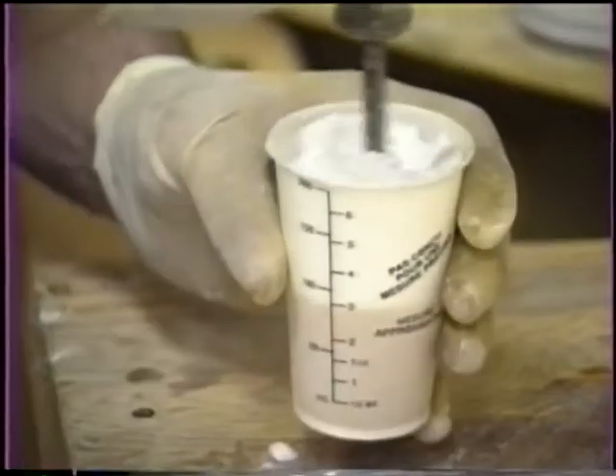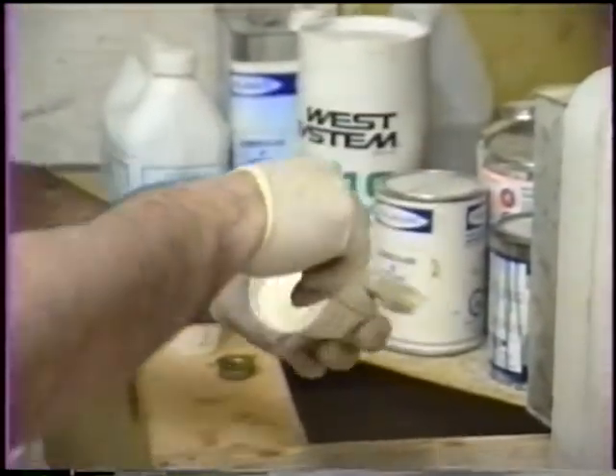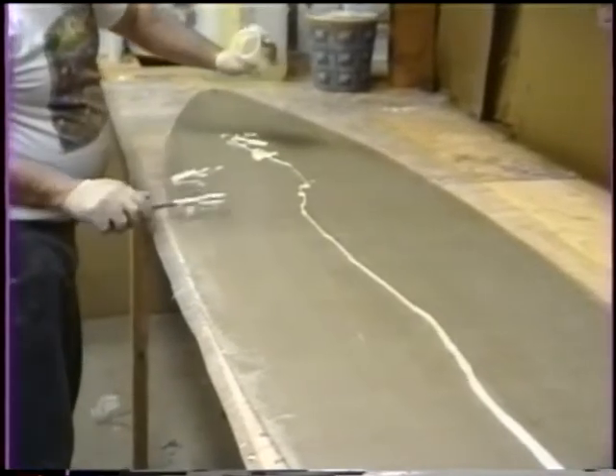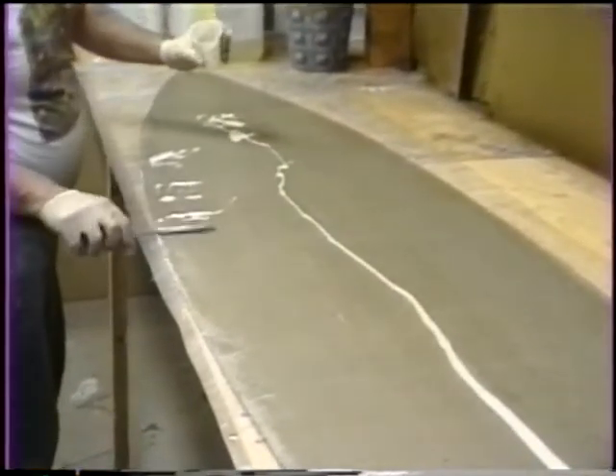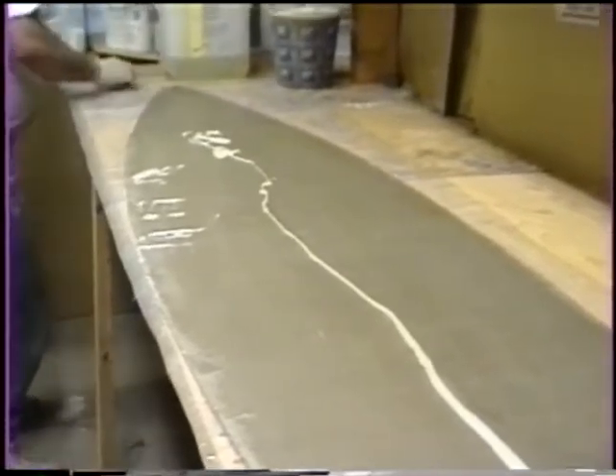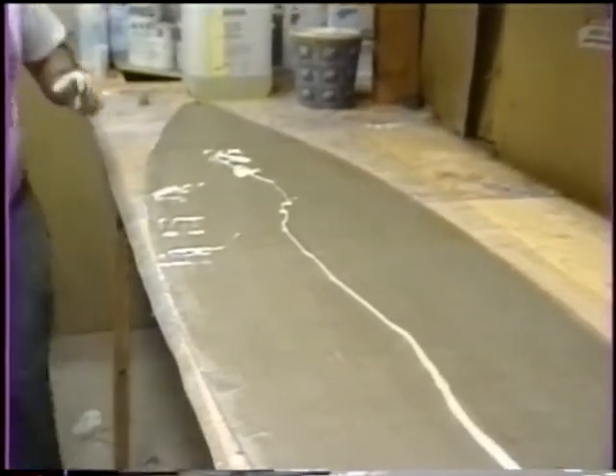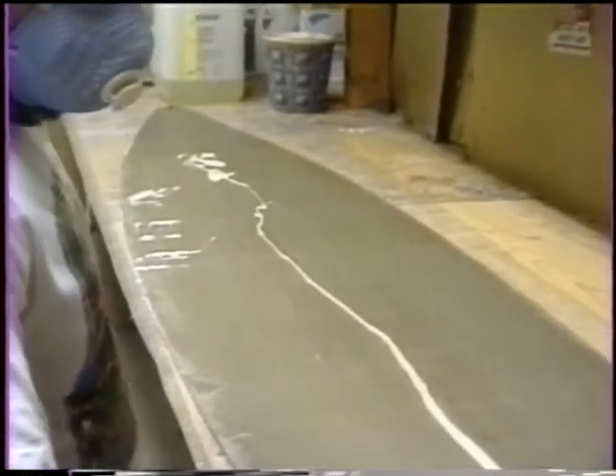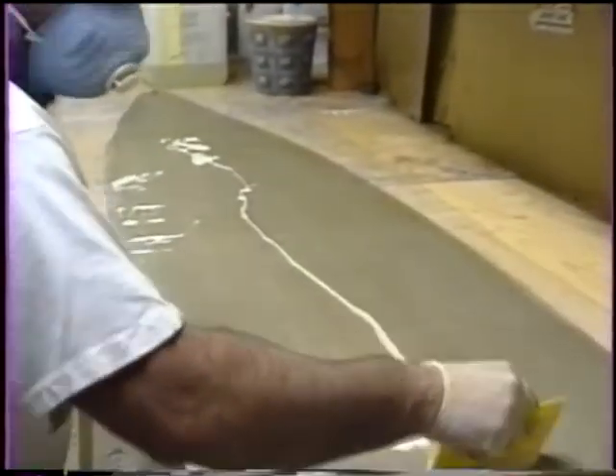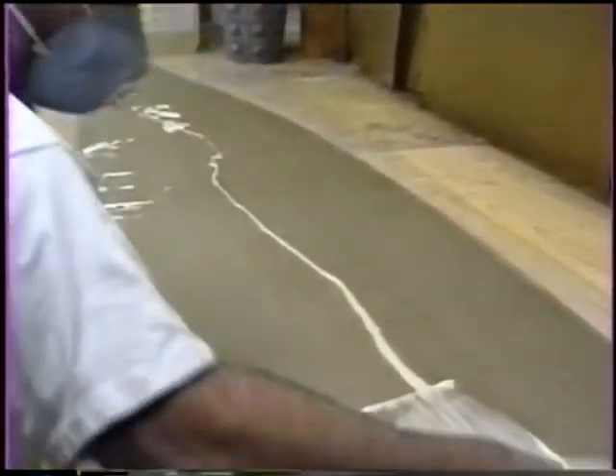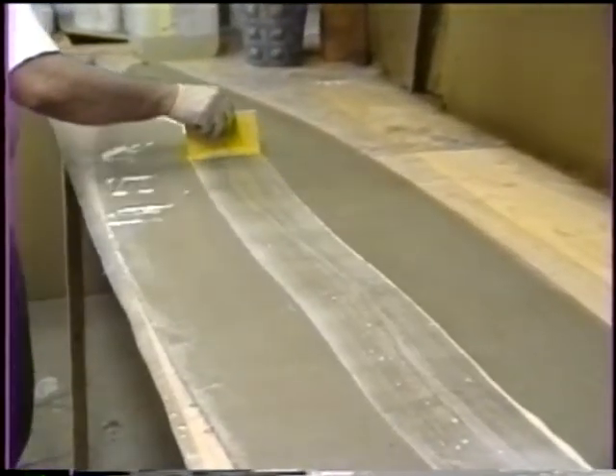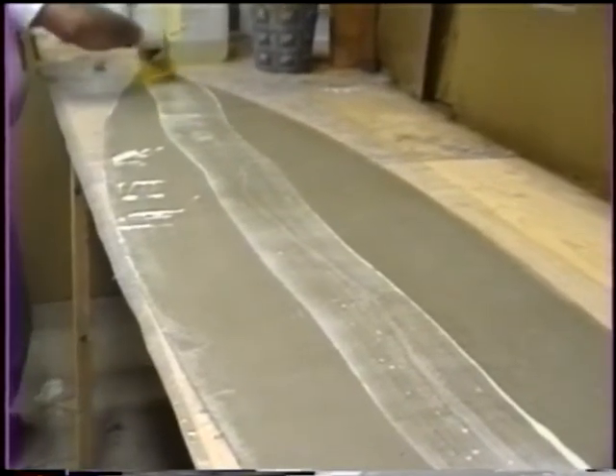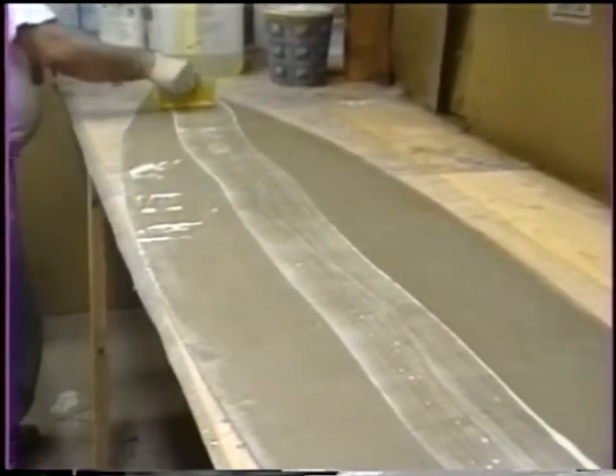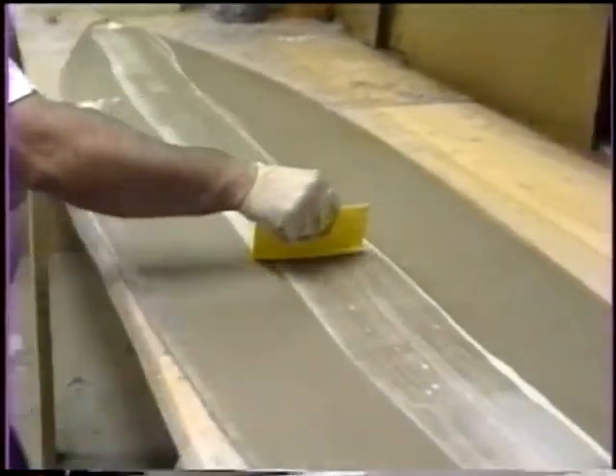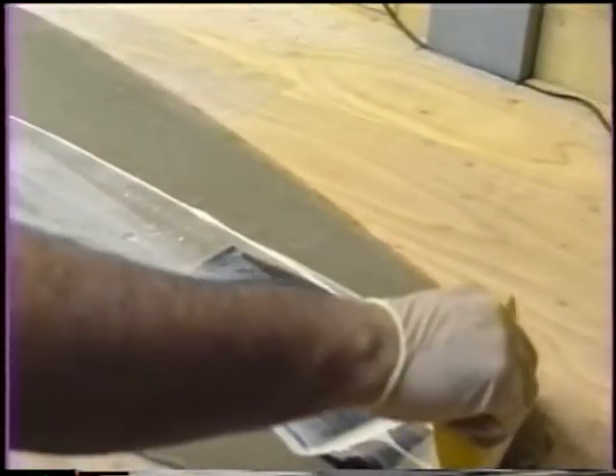Some weight-saving and bonding tips are to mix up microspheres with some of the resin and fill the coarse surface of the high-density foam before covering with cloth. Another tip for a long-lasting board is to install a long 1.5 inch deep, 1/4 inch high-density foam stiffener routed into the styrofoam bottom. Wrap this with a 5 inch wide cloth strip, wet out and install. By folding back the extra wet cloth onto the blank, it will form a T-shaped reinforcement, which will strengthen and protect the bottom from delaminating.